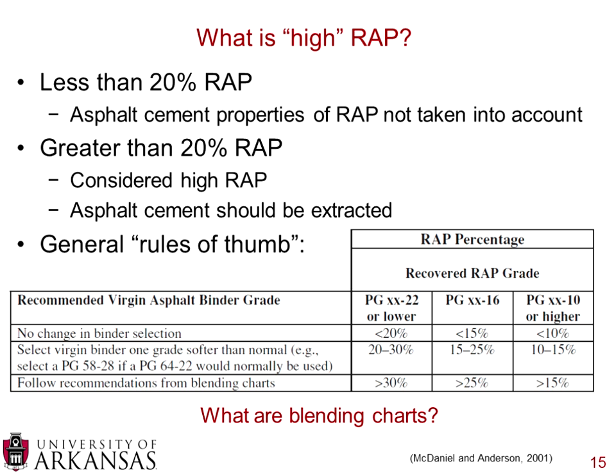you'd bump that down to a 52-28. So if you're using a 58-28, you would want a softer asphalt, and you'd go down to a 52-28. The example here they have in the table is if you were using a 64-22, you would bump that down to a 58-28. And for the minus 22 binders, you use 20 to 30% RAP, bumps that grade one grade softer. If you're using a minus 16 binder, it's 15 to 25%. And if you're using a minus 10 grade binder, it's 10 to 15%.